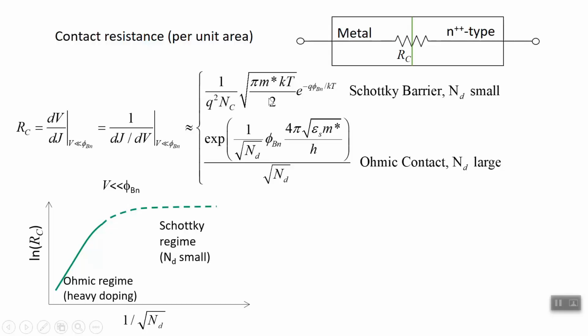So if I made a graph now of how the contact resistance depends on the doping, we'll take the logarithm of it. For an ohmic contact, for very heavy doping, its logarithmic behavior will be linear. But the thing I want to bring your attention to is that in the Schottky barrier regime, that is small doping, the contact resistance is independent of the doping level. I mean, it's nowhere in the expression, right? So it levels off. I'll draw the log of contact resistance versus not doping, but 1 over the square root of doping, all the way from very heavy doping to very light doping. And it makes a continuous transition from being ohmic to being Schottky. And when it's Schottky, the doping level has no effect on the resistance of the junction.